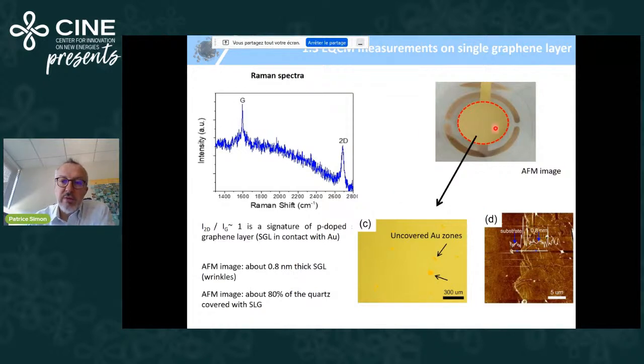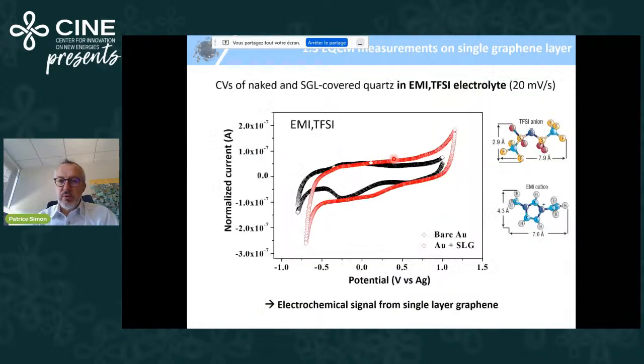We use the same setup, electrochemical quartz crystal microbalance. And this is an optical image of a gold quartz coated with single layer graphene. There are some slight 15% of uncoated gold zones. But we see from the Raman spectroscopy results that we have a p-doped graphene layer signature, which is normal because we have a gold below in contact with the SLG. And the AFM shows some wrinkles, about 0.8 nanometers. But anyway, 80 to 90% of the quartz is coated with graphene.